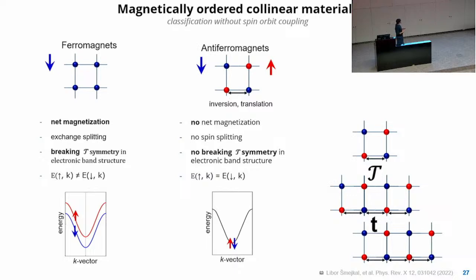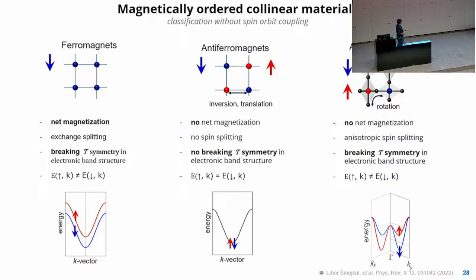And now Libor figured out that people actually forgot something when they did this kind of symmetry analysis. And what they forgot is, as trivial as it may sound, they didn't consider all the atoms in the unit cell. So it turns out that if you consider, in addition to these magnetic ones, also the non-magnetic ones, you can find cases where you still have this magnetic compensation. So you still have half of them blue, half of them red, but you still have a different kind of symmetry. And the difference is, now we still have no magnetization, so we have one property from these antiferromagnets, but we have the breaking of the time-reversal symmetry like it was in the case of the ferromagnets.